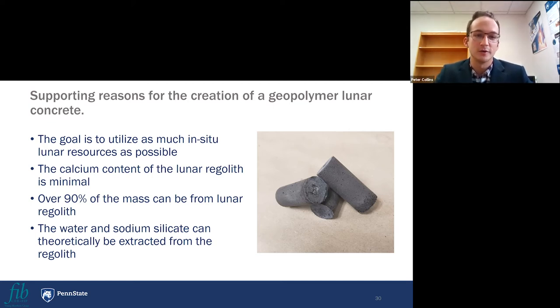So we want to use the in-situ lunar resources that are available to us and find a way to make those work instead of bringing stuff from Earth. And the creation of something like an ordinary Portland cement on the moon is just not really possible. One, between the technology, the cement set up like a cement batch plant and cement kiln and all that to produce the cement is just technologically not the most feasible option, as well as the calcium content in lunar regolith is really minimal. If you remember the XRF analysis from a few slides ago, the calcium content is like 9%, whereas in an ordinary Portland cement, calcium oxide makes up about 60%, I believe, of the overall constituent.